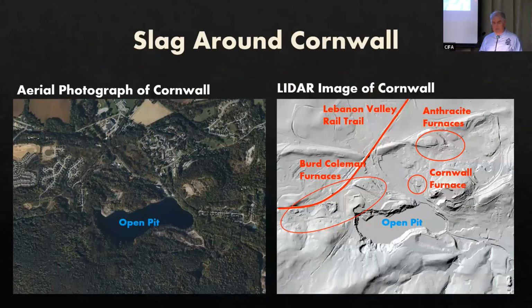Now, using a little bit of geologic detective work, you can even see the remaining piles of slag near those furnaces using remote sensing tools. It's difficult in the picture on the left, which is of Cornwall, where you see the open pit, to see these slag piles. However, that's an aerial photograph. If you use a laser imaging detection and ranging image, otherwise known as a LiDAR image, you can see remaining piles of slag near each of the blast furnaces in Cornwall. I've circled them in red, so you can see Cornwall Furnace is the smallest, and then you see Burd Coleman furnaces and also the piles near Anthracite Furnace.